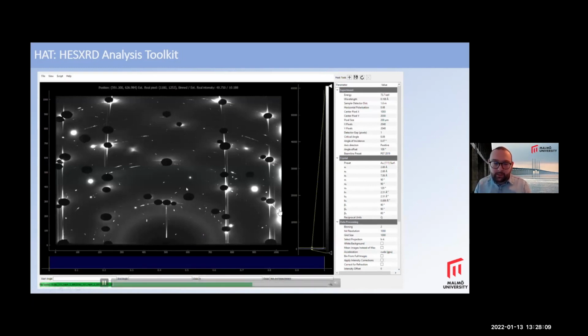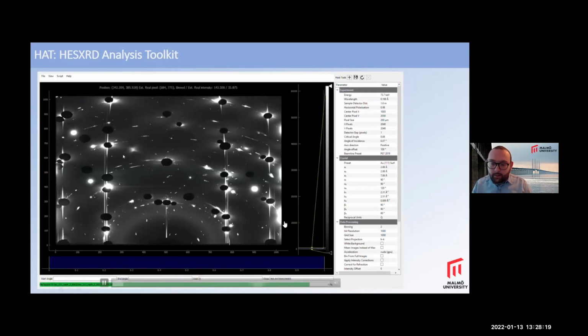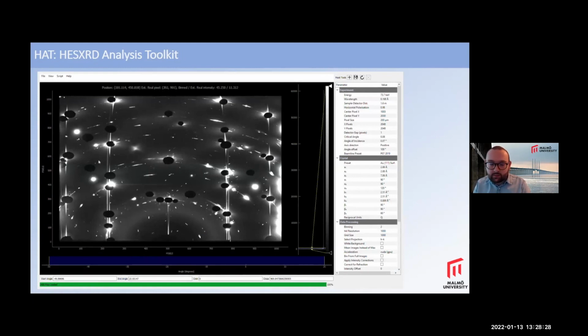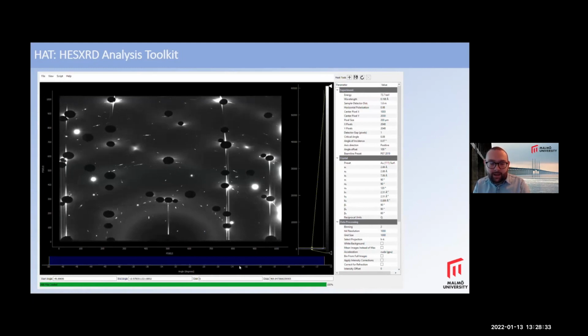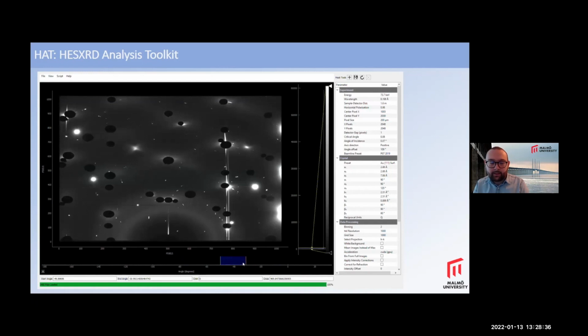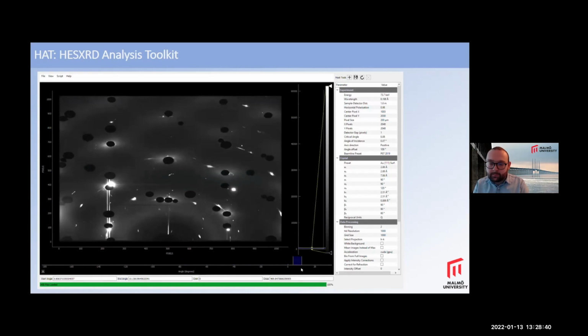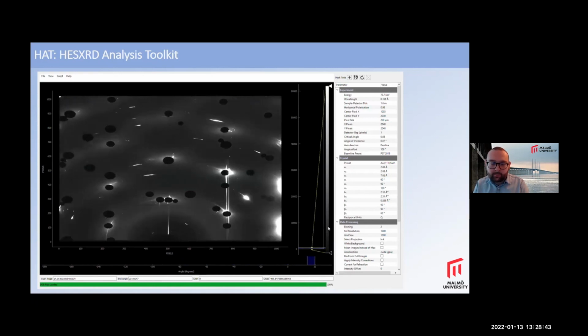I'll play this movie, and this is called the High Energy Analysis Toolkit. I've skipped some of the loading for you, but basically we can use it to analyze this high energy surface X-ray diffraction data. If you hover over a pixel, you can get the intensity and the position. Now it's loaded. You can change the angular range and explore your data set by scrolling through it here. You can see this is like the scan I showed you before.